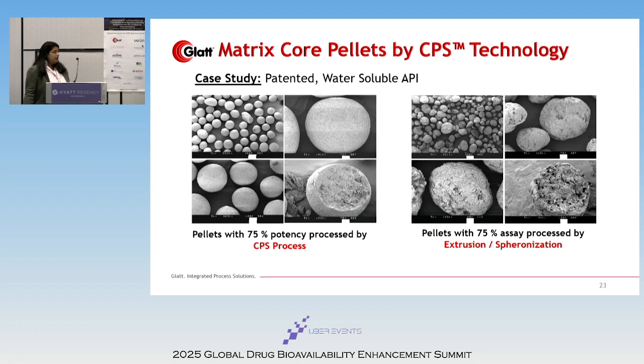So again, coming to a case study. This is a case study where we wanted to see if you can incorporate high dose into the CPS and also compare between extrusion and spheronization against the CPS process. Here you can see that when we use the CPS process, we get a perfect sphere. And with the extrusion, you can see some porosity over here. So there is a slight advantage when you use a CPS process.